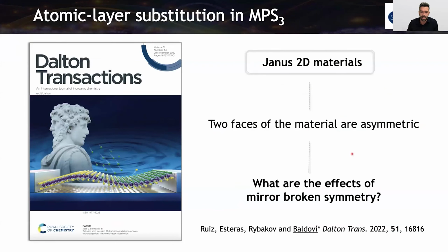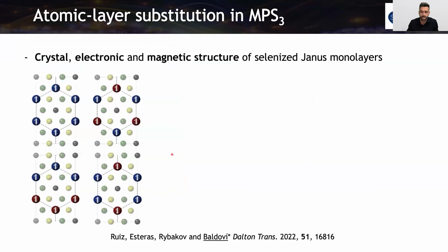Another idea with this material that we proposed was to study what happens if we have a Janus structure. So similar to molybdenum disulfide, for example, we substitute in this case sulfur by selenium, and we wanted to see the effects of this mirror broken symmetry in the material. This was published in Dalton Transactions, and this is the cover with the Roman god Janus that is looking to the future and the past, because this material has now two faces.